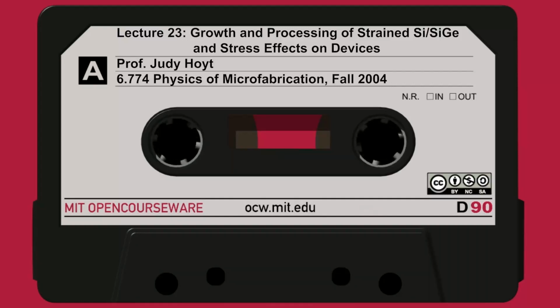Again, if the silicon's thin enough, it will now stretch in X and Y to match the lattice parameter of the substrate, and it will compress in Z. So we call this silicon layer, epi layer, as being under biaxial tension. And again, if you grow it too large, the bonds will no longer stretch. They'll break. You'll get dislocations. Silicon will go back. Instead of being stretched, it'll go back to its normal lattice parameter. At that point, it'll be relaxed.